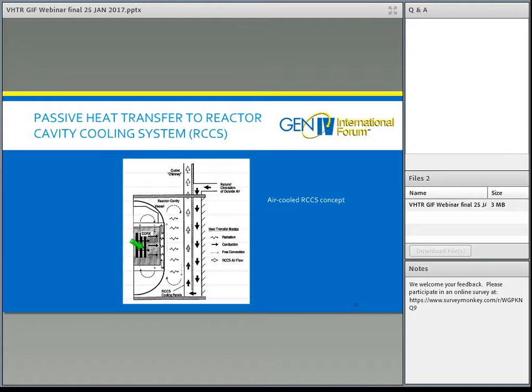So from the core itself through the graphite, we see the conduction of heat through the material. From the reactor vessel or the reactor core to the vessel, we see the radiation of heat onto the vessel surface, and then from the vessel surface to the reactor cavity cooling system, a transfer of heat both by radiation and by the circulation of warm air within the reactor cavity, which also transfers heat onto the reactor cavity cooling system. Again, a very oversimplified cartoon diagram of this.